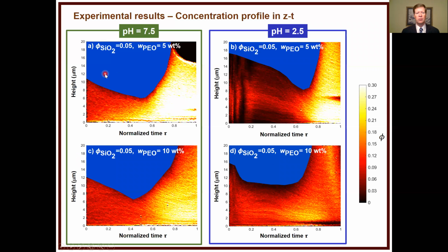If we look now on the left-hand side, this is pH 7.5. On the right-hand side, it's pH 2.5. The ones on the left look very similar. In fact, even in the upper left one, you can see that interface come down, and there is some pushing of particles that are partitioning at the surface. That's mainly because the Péclet number is greater than 1. And then we just didn't see that surface come all the way down because the volume fractions and the thickness of the film were higher than what we're presenting here.